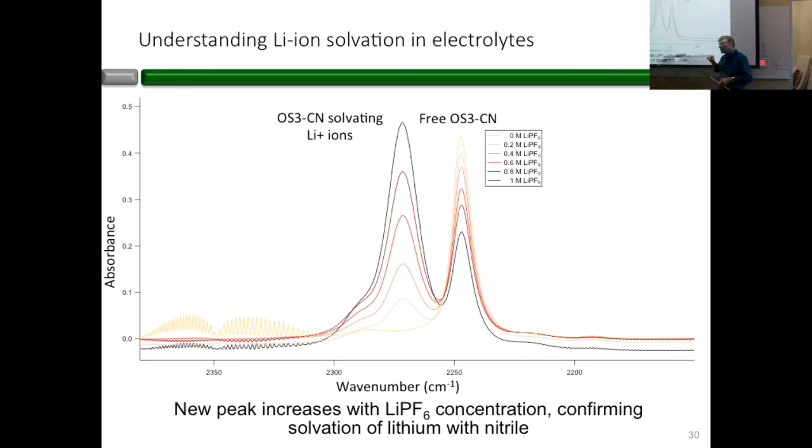If that lithium tries to pull solvent in between the sheets of graphite, the graphite flakes expand and they break. So understanding the thermodynamics of how these different groups interact with the lithium, you want the interaction to be small enough that they are functionally carrying the lithium between the anode and the cathode, but you'd also like that solvation or that interaction to be weak enough that when the lithium goes toward the SEI layer, it can easily remove those solvent molecules to go through the SEI layer and then into the carbon.